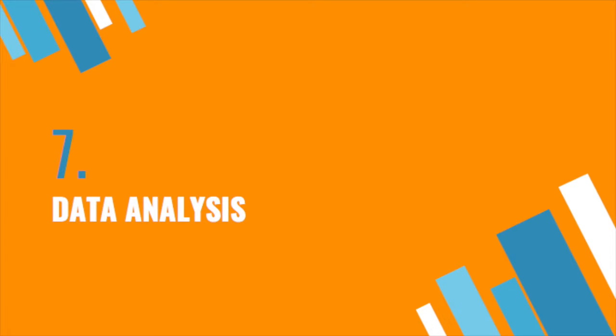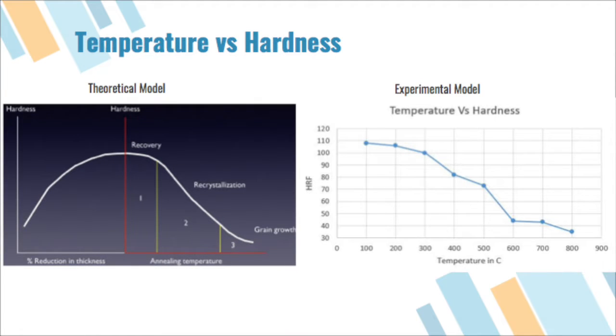The first part of the results obtained and analyzed the hardness at different temperatures to understand the graphical curve and to observe where the recrystallization process occurs. On the left is the reference model and on the right is the experimental, where it shows a reasonable resemblance. The recovery, recrystallization, and grain growth can be seen.